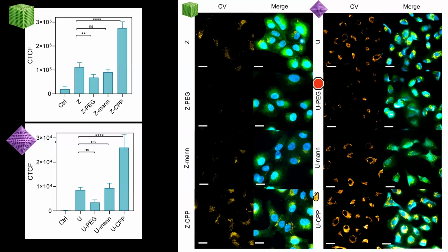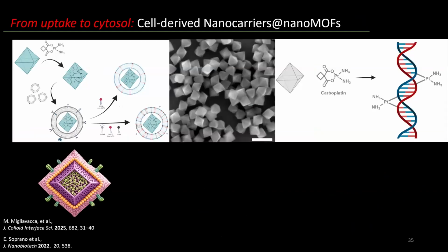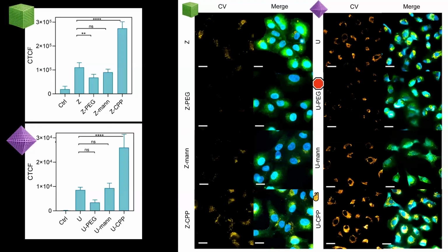Okay. And with nanoparticles, we were making 2D libraries, 3D libraries by changing different aspects of hydrophobicity, elasticity, charge, anything that you can imagine. And in this particular case, we simply change the molecules that you have on the surface of the MOF to see if it has an impact on the amount of cells that you have inside. The idea was Z is ZIF, U is UIO, because we wanted to compare similar shape and size. So this is without anything on the surface. And then when we put PEG, uptake goes down. Sorry. That is something that we were expecting.